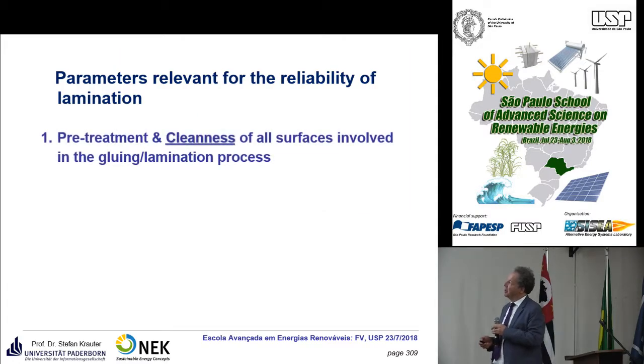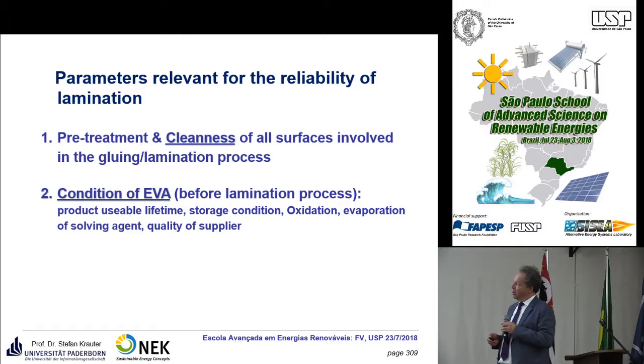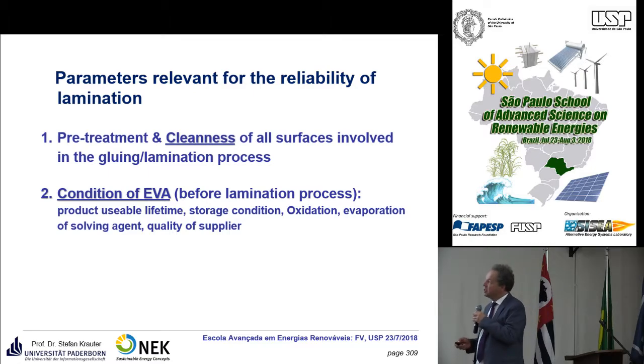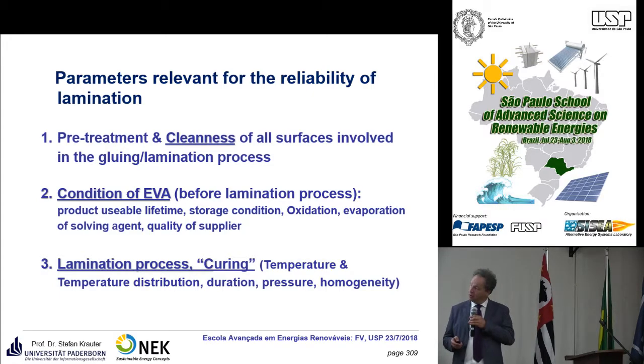Lamination can cause stress. Lamination is also a problem for the durability of the module if the module is not clean. You know, with every gluing process, if the surface is not clean, it won't last long. You have to make sure of this in order to get a good module. Also, the plastic material, the EVA, has only a limited lifetime before processing because the additives will evaporate. So you have to make sure that you use it within a usable lifetime. The storage condition is important. There could be some oxidation of the material, also some evaporation of the solvent, and also the quality of the supplier. Some suppliers have very fluctuating quality, so this makes it difficult to have a good quality.